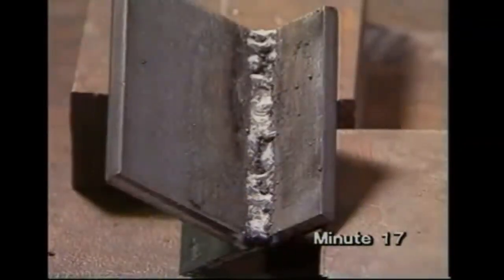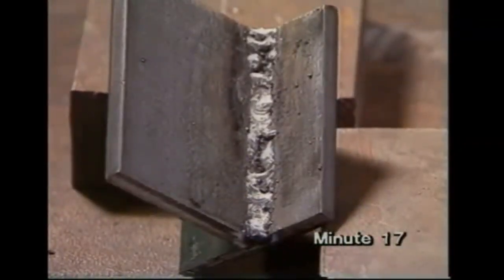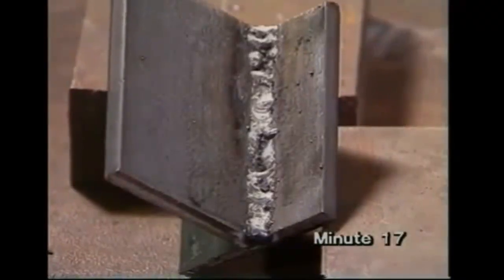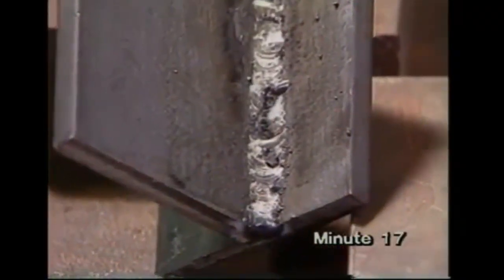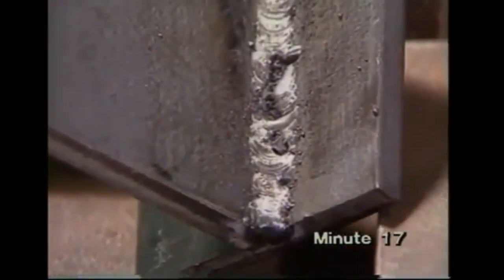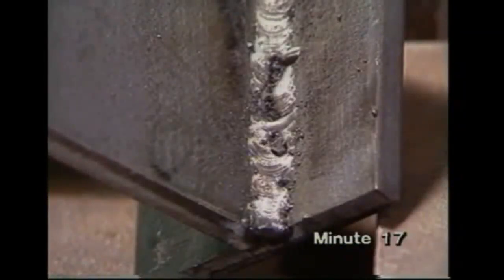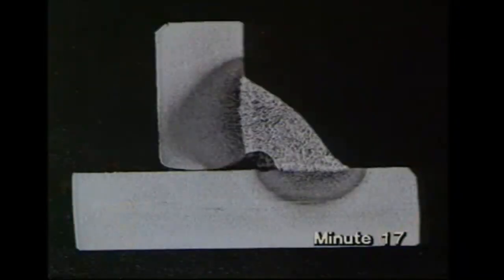If the arc is too long, when you weld a joint, it's even worse than welding on a flat plate. The weld metal has a rough surface and doesn't melt in properly. The slag is trapped inside the metal. The slag and poor melting show up in a macro section. The weld will be weak.